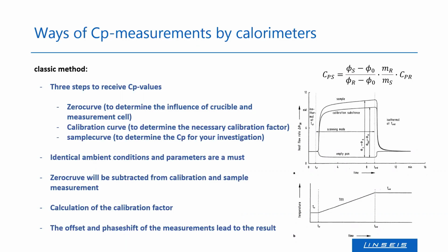So we are checking the rise time here. And above you can see the 3 measurements you need. At the bottom you can see the empty pan, so without anything inside, just the measurement cell and the pan. And a bit higher you can see the calibration substance and the sample. So what we already can see here is the heat capacity is higher in this case for this specific sample with this amount, so with this mass, than the calibration substance.